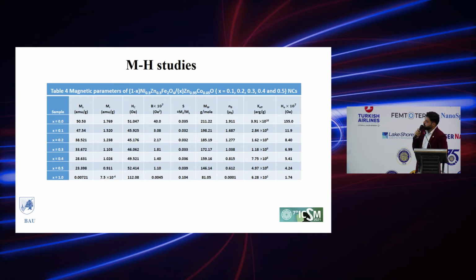The squareness ratio was much less than 0.5, which infers that we have spin canting effect in a large number of the grains of the nanocomposites. And the magneton number has also shown a decrease compatible with the variation of MS. And the effective anisotropy constant has also shown a decrease with the increase in the amount of the added zinc cobalt oxide in the nanocomposite.